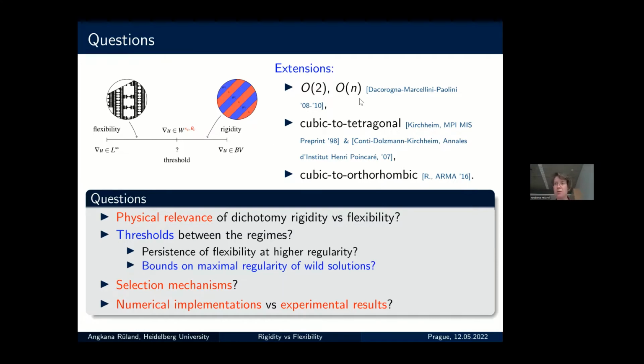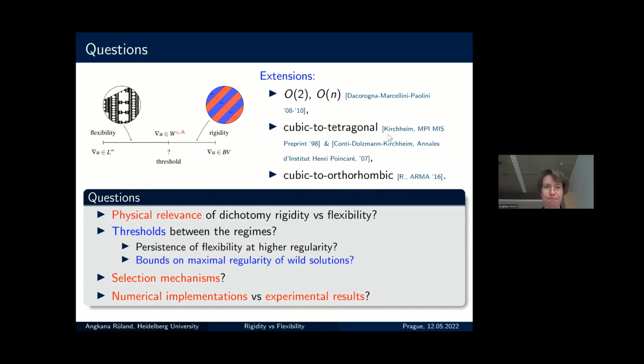So this is a quite well understood situation, but it arises also in many other phase transformations which are not two-dimensional but really three-dimensional, and arise in real experiments such as the cubic to tetragonal phase transformation or the cubic to orthorhombic, to name just a few. So it's really an interesting situation also from an experimental point of view. Okay, and so one can push, as I said, both from the flexible regime and from the rigid regime. In this talk, I would like to push mainly from the rigid regime, showing how function spaces relate to certain scaling laws and scaling law behavior, and discussing a particular example with the Tartar Square. But of course, one can also push from the flexible regime and try to see whether flexibility persists at positive Sobolev regularity.